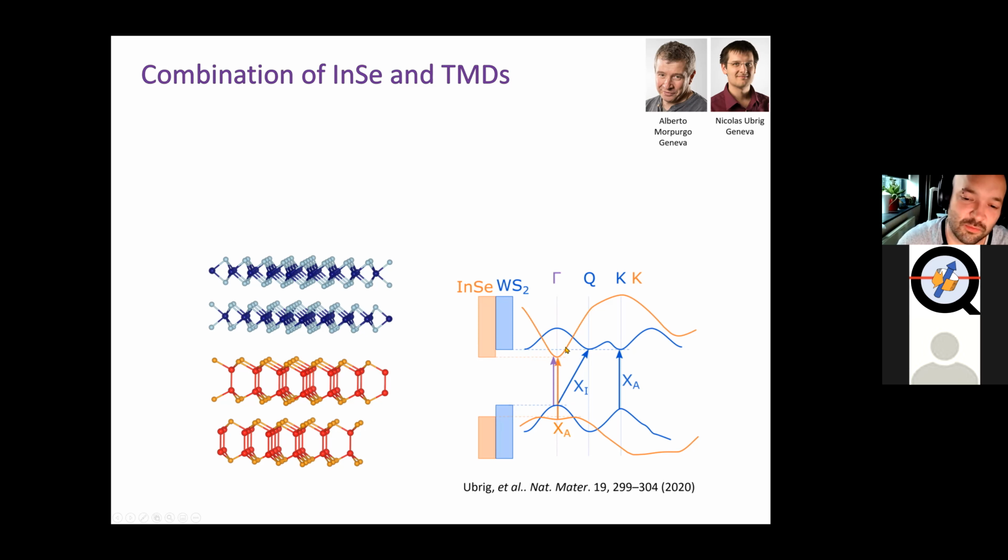Now, this is trying to address the problem when you grow these materials and you cannot control the twist angle for some reason. The properties would be hugely dependent on the twist, but in this system, they're not, because everything happens at the gamma point. And of course, in K-space, everything rotates around gamma points. So when you create a system like that, it's basically invariant to the rotation between the crystals. And so that is what has been measured here.